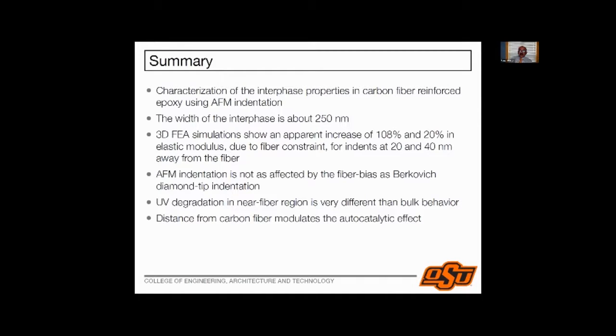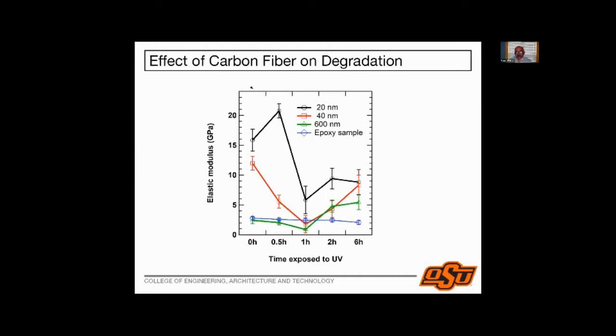When we look at UV degradation, we find that UV degradation in the near fiber region is very different than the bulk behavior. And the further you are from the carbon fiber, the autocatalytic effect that happens because of UV degradation from the carbon fiber is different, right? Where do we go next from here? It would be nice to be able to fit autocatalytic kinetic mechanisms to this, because this is data that is observed at very small length scales and very short time scales, and then figure out if we can actually predict the autocatalytic effect of the carbon fiber on the UV degradation behavior.